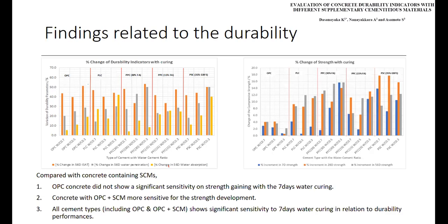So you can see here, if I take the water absorption results, the amber color, you can see even up to 40% we can achieve with the utilization of water curing, proper water curing. And the strength gain also did the same kind of way. Only difference is that here we have tested for durability parameters. Here we have tested for strength gain.